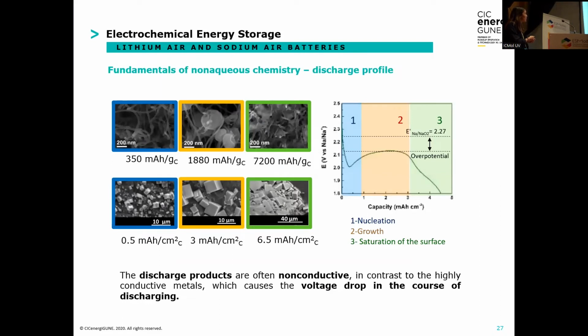Here you can see a typical discharge plot for metal air batteries. As I said, this is a conversion reaction, so we are not moving the ions, but we are forming oxides. In the case of the lithium air, we have lithium peroxide. And as we go deeper in capacity, we can see that these discharge products grow. First we have the nucleation step, where we are nucleating small particles on the surface of the carbon electrode. Then the flat plateau is when these particles grow, and the longer, the higher this plateau, the higher the capacity and the better our battery, until it reaches a saturation point. This is where all the cathode becomes clogged with these particles, and the battery is going to die.